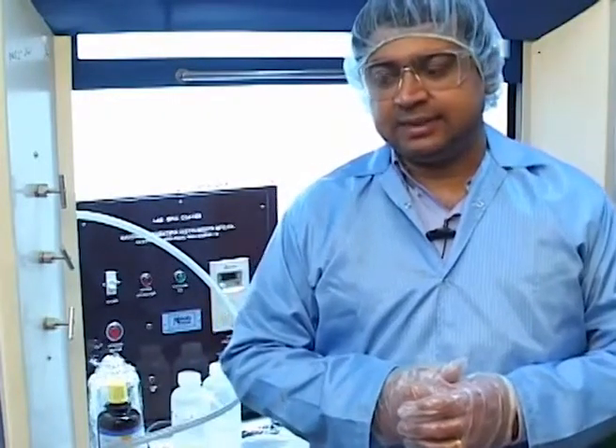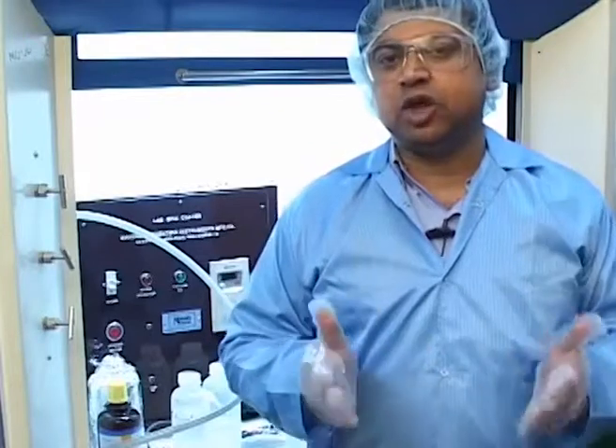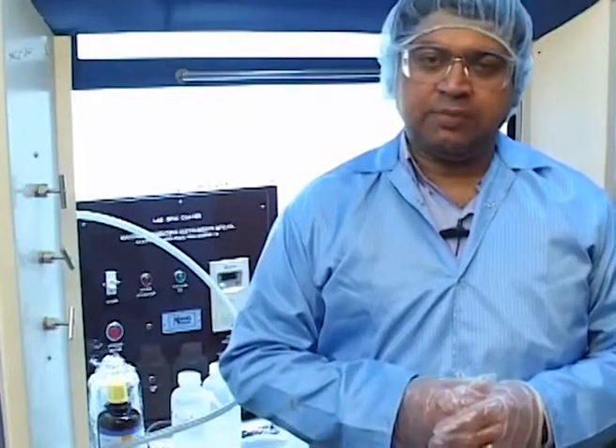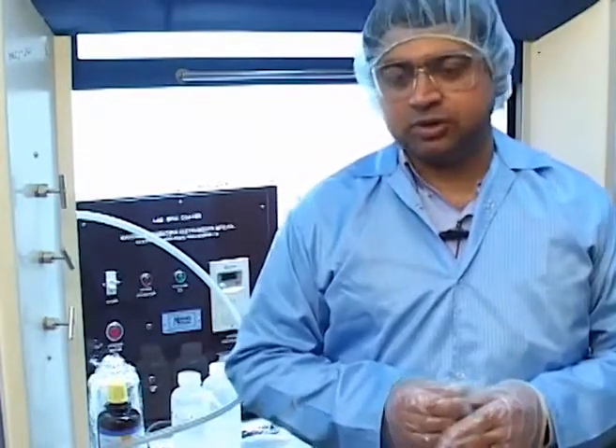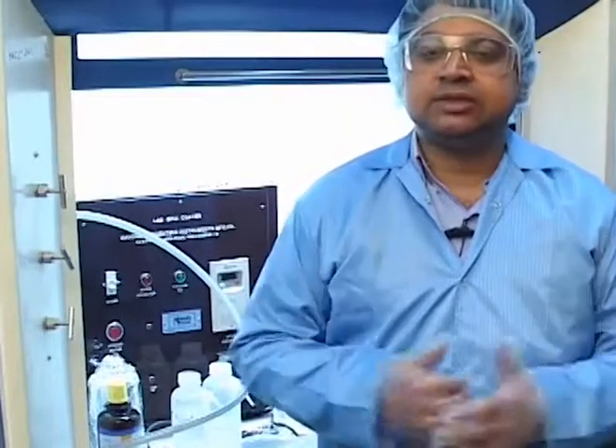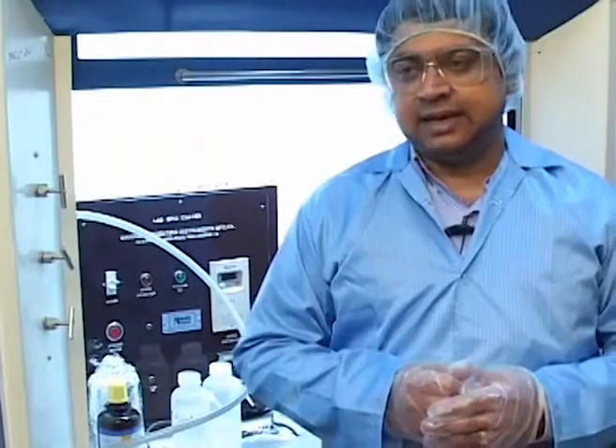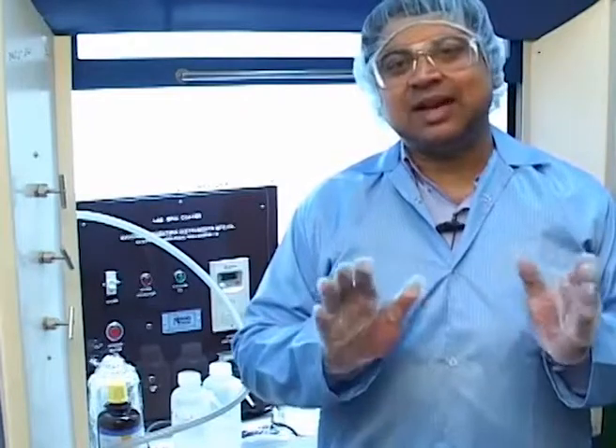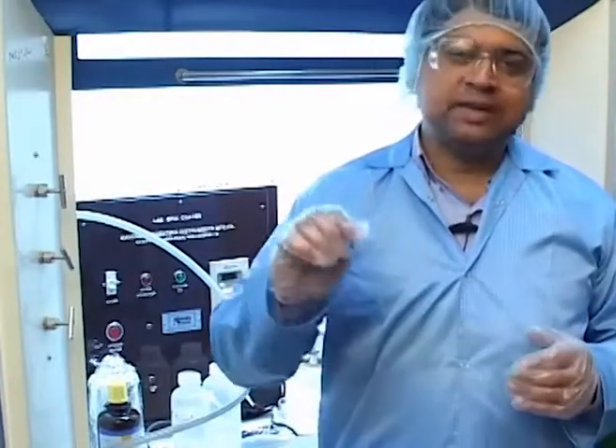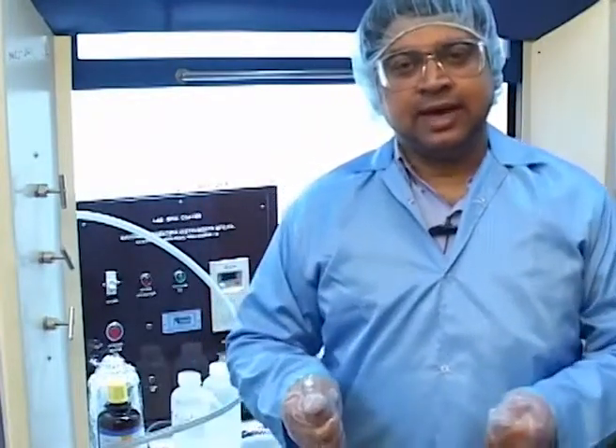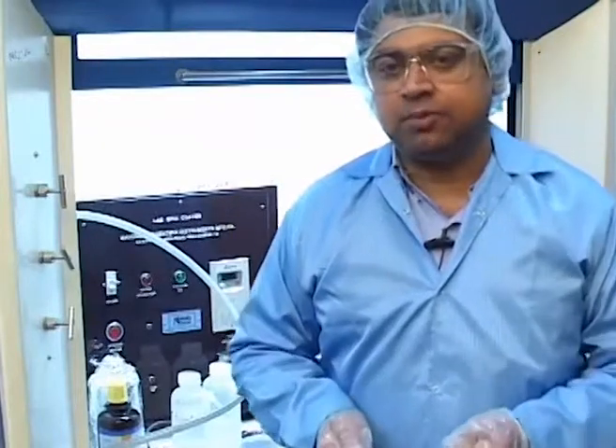Essentially, the Piranha is prepared by mixing 3 parts by volume of sulfuric acid with 1 part by volume of H2O2 or hydrogen peroxide. It's a highly exothermic process and results in a lot of heat release and fumes. And once the solution stabilizes a little bit after mixing, we typically use a glass rod to stir the solution and put the wafer in the solution and clean it for several minutes, about 6 to 7 minutes, so that everything which is organic on the top goes away.